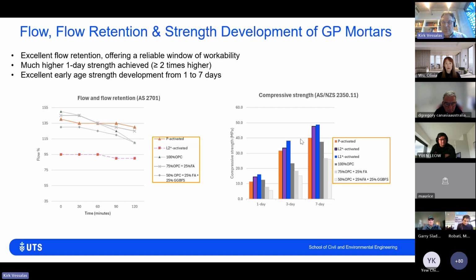The thing that Dave mentioned before, if we just move over to the right, is the excellent early age strength that we get. And when we see the cluster here, the orange, purple, the blue, we can see that these geopolymer systems, powder activated, a liquid activated system, a different variation 2 versus variation 1, we see that basically these strengths here are much higher than the conventional systems here.